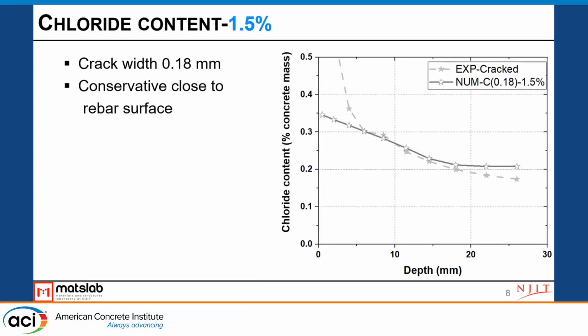With this numerical approach, the first result we want to look at is the chloride content. The first one we are looking at here is the chloride profile of the 1.5% surface chloride concentration. The figure we are looking at here has a crack width of 0.18 millimeter, and the y-axis is the chloride content measured in percentage of the concrete mass, and the x-axis is depth to the exposure surface.